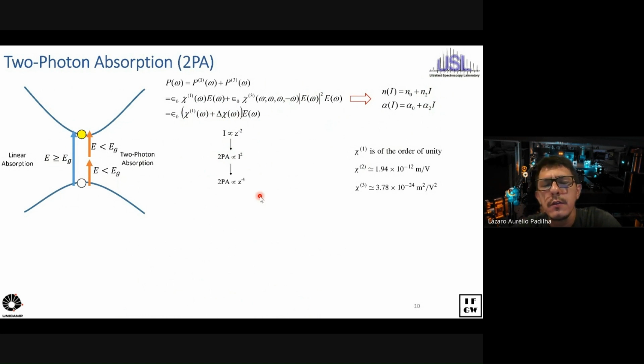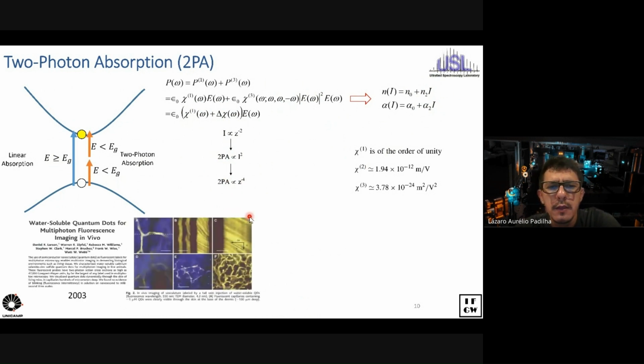So the emission due to two-photon absorption is proportional to z to the minus 4, which means that you can get very good resolution on two-photon emission if you have a focused laser beam. People have explored this in the past for like 20 years, using two-photon absorption or two-photon excited photoluminescence to look into materials for imaging with 3D resolution.